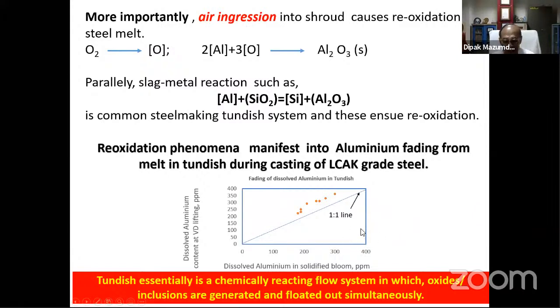Now, therefore we understand that Tundish is not an inert reactor. In Tundish, this sort of reaction takes place. So per se, Tundish is a reacting multi-phase flow system, because we have gas-liquid flows, because air entrainment takes place, and I will show that air entrainment is very common in steel industries. It is not zero per se. So therefore, we can expect that air entrainment will take place, aluminum fading will take place. So treating Tundish as an inert reactor is a gross simplification.